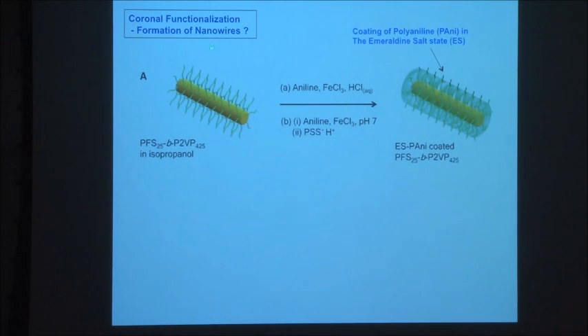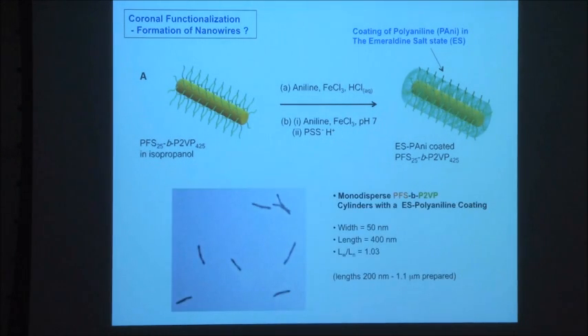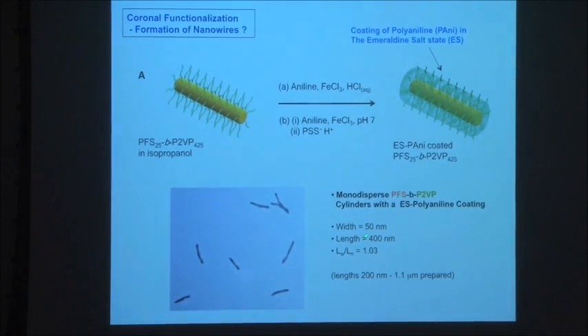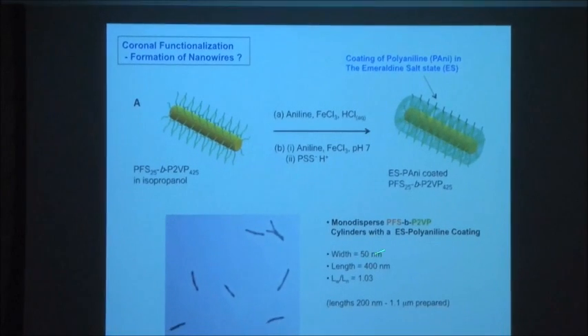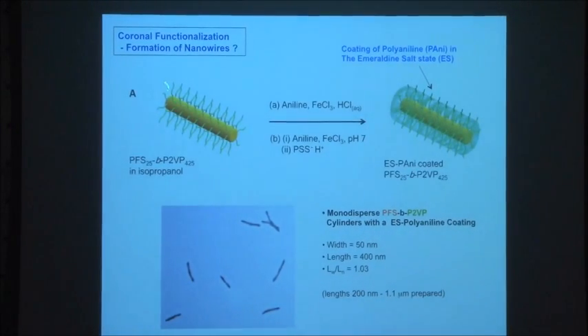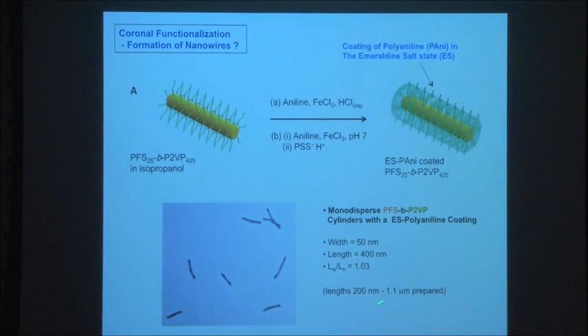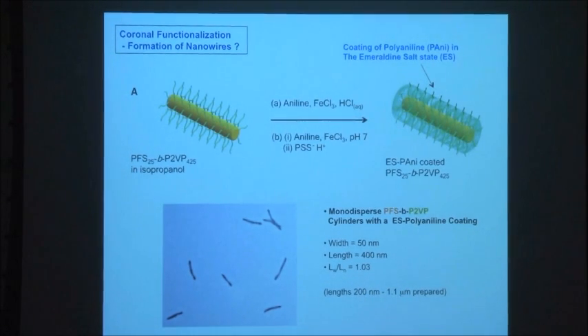To illustrate coronal functionalization, you can actually make well-defined nanowires from these structures. The way we've done this is to make well-defined cylinders by crystallization-driven self-assembly of PFS-poly-2-vinyl pyridine. And then we've templated the growth of conductive polyaniline in the emeraldine salt state around the cylinders so that you get well-defined nanowires. And these are the types of structures that you can make. These ones here are of length 400 nanometers, width 50 nanometers. So you can vary the lengths here using crystallization-driven self-assembly. We've made these of length between 200 nanometers and 1.1 microns. So this is just one example of the materials.